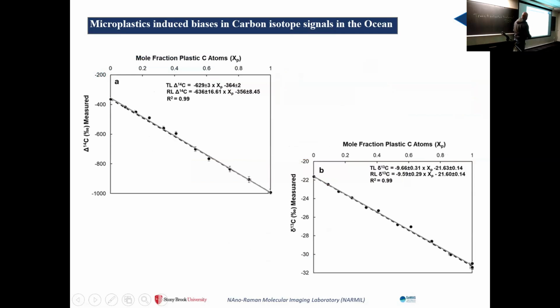What you see in these plots is kind of the same as what I showed you before. You have the mole fraction of plastic carbon atoms. This is the amount of carbon atoms in our samples that we added to those samples. And this is the delta 14 carbon measured. So this is what the equipment gives us, the experimental value. Again, the solid red line is our theoretical values, and you see how our experimental results fall with our theoretical expectations.